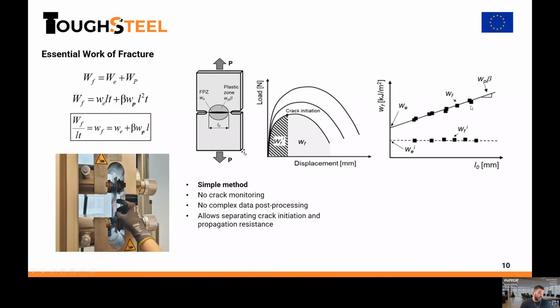Well, the most interesting part of this method is that it's a simple method compared to the other fracture mechanics standards, but mainly because you don't have to monitor or follow the crack advance during the whole test. So you can test specimens up to the final fracture and then measure this energy, and you can easily evaluate this essential work of fracture.